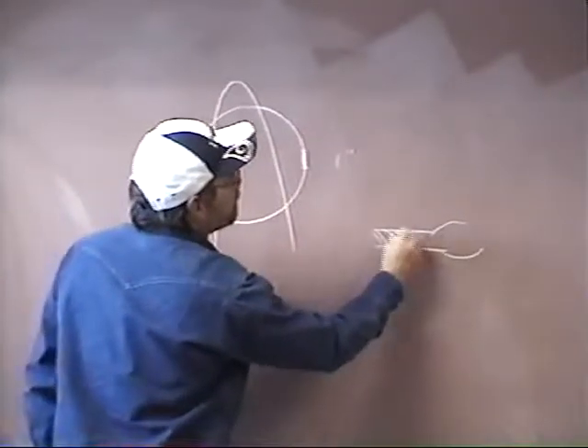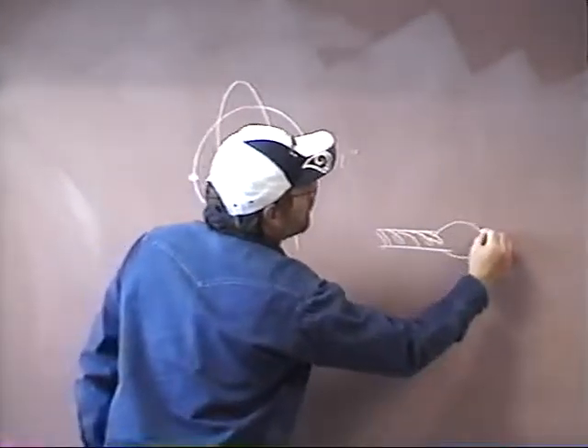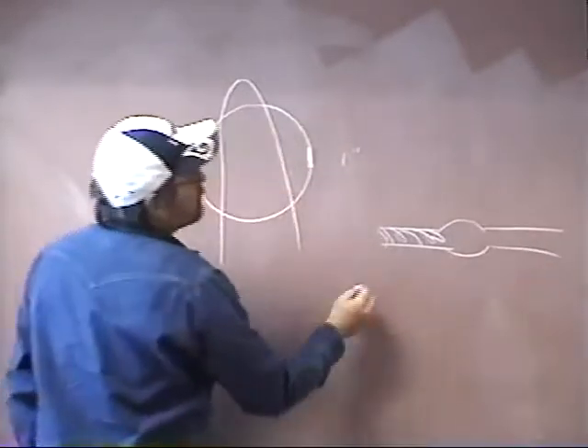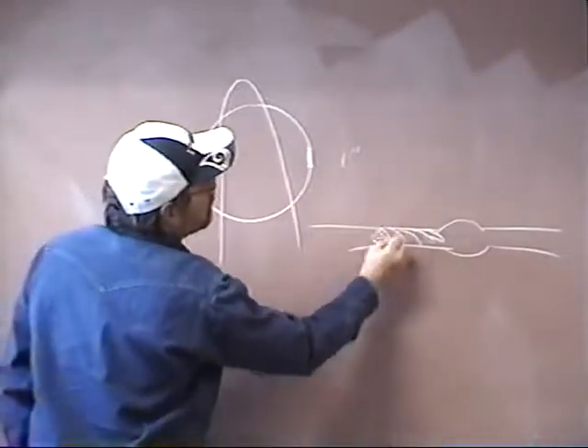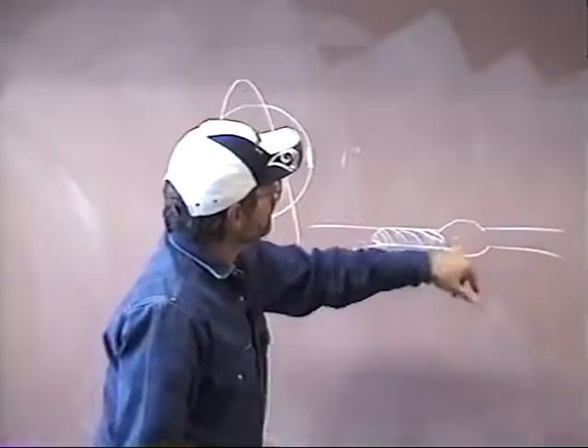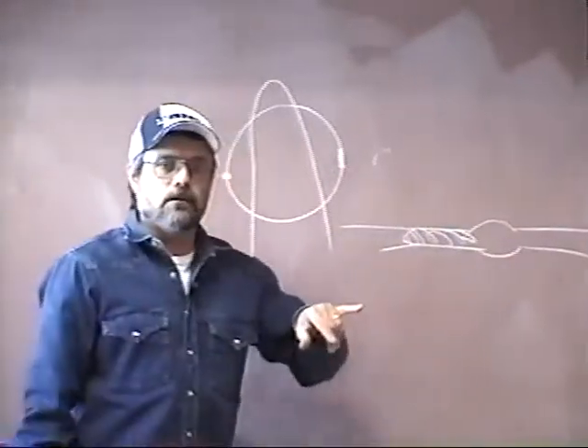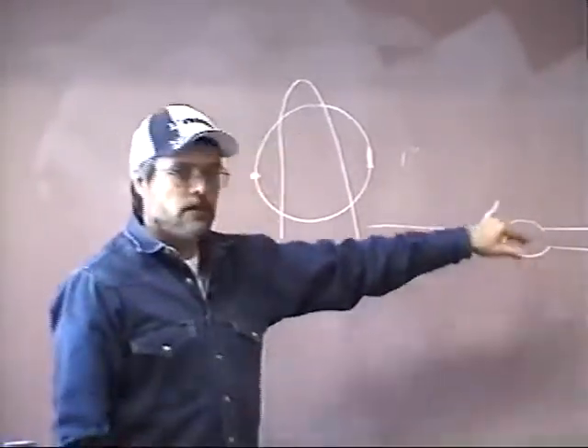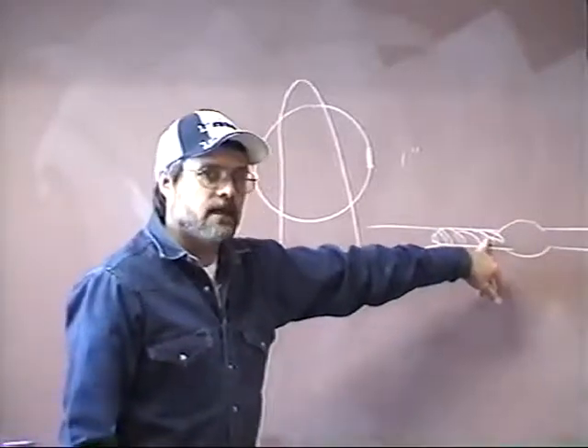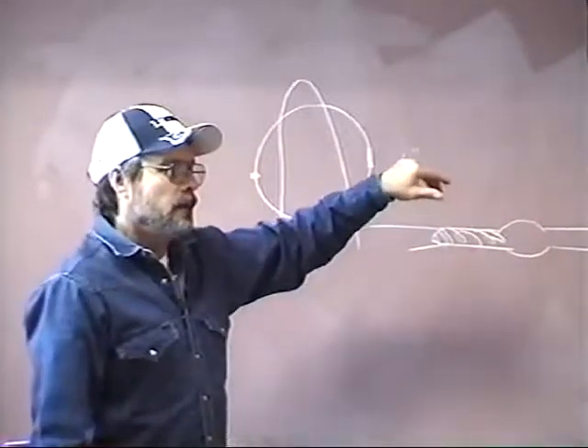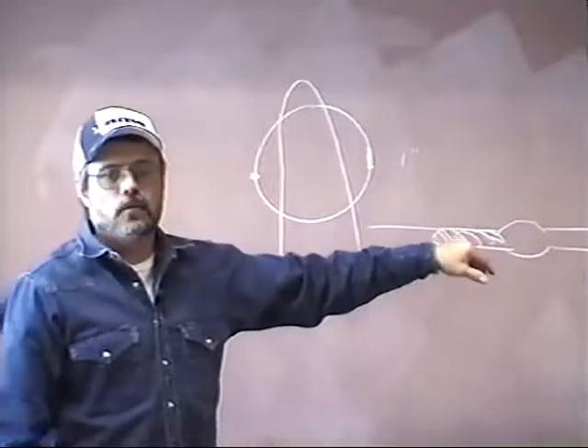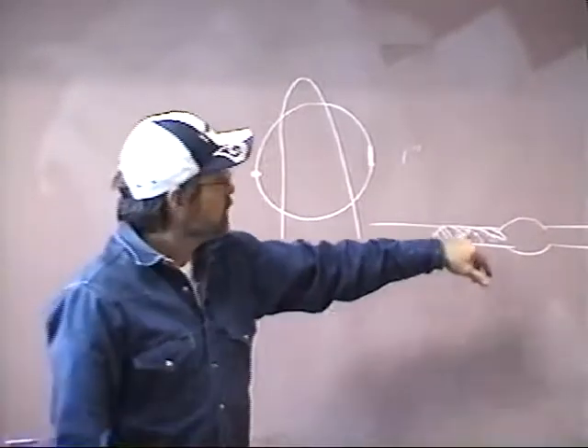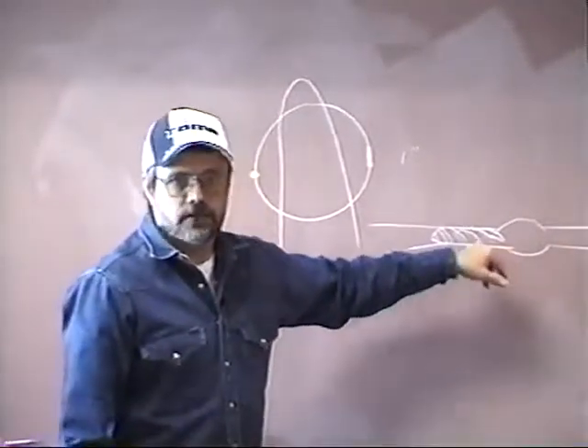Here's your tack, and your bevel goes on like that. Here's where you started. But you've poked that welding rod through and you've opened up the keyhole. The reason we open up that keyhole is so that we can make a good tie-in to that tack when we come out. Most of the problems I see in the welding lab are from people coming in and going out of these tacks.